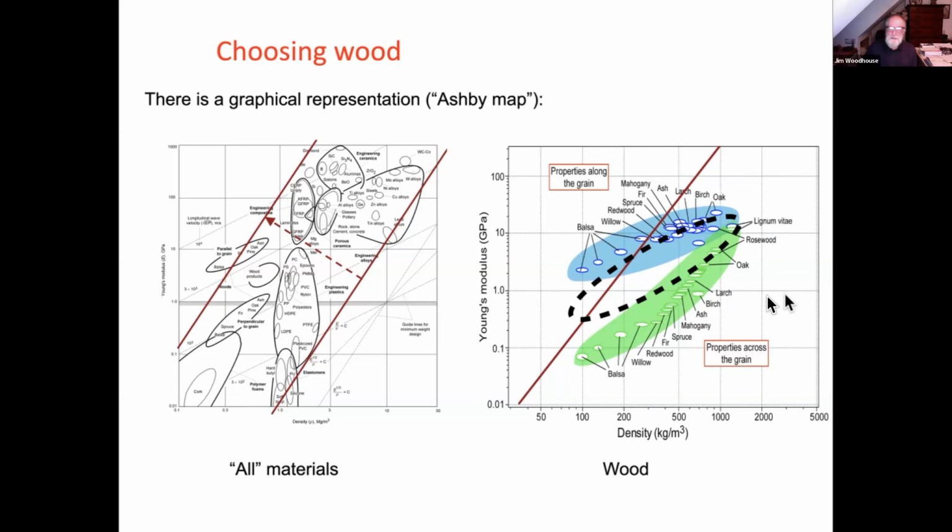Because on average, all the modes use both stiffnesses in a rather balanced way. And the way they combine in the formula for the frequencies and to get this modal density more or less depends on this geometric mean of the two stiffnesses. And so all things being equal, if you're only measuring along the grain, then if you choose the lightest, you're not going to get the optimal. It would be somewhere in the middle of the range. Is that possibly right? True?